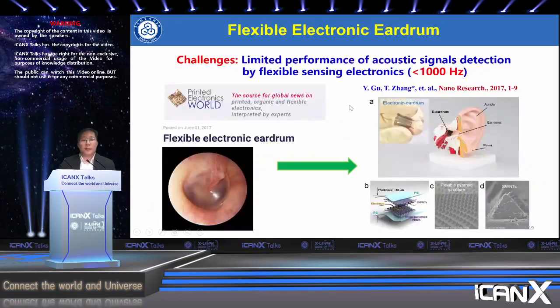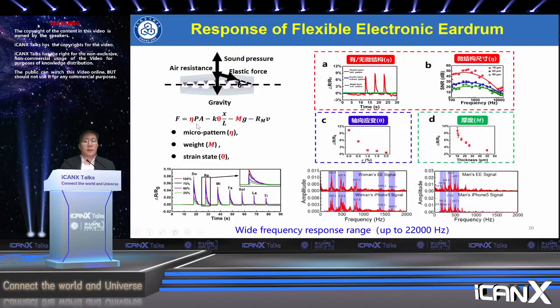So for the low-frequency signals such as heart rate, pulse, and also your speech, it's okay for the device. But for the high-frequency signals, such as acoustic signals above 1000 hertz, we have to optimize this device. So in this work, we developed what we call the flexible electronic eardrum, and we developed mathematical models at the interface of these devices. And we found that the micro pattern, the size, the strain state, and also the thickness play a very important role. We did experiments to verify these parameters.